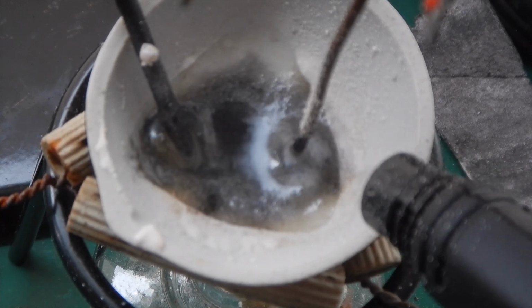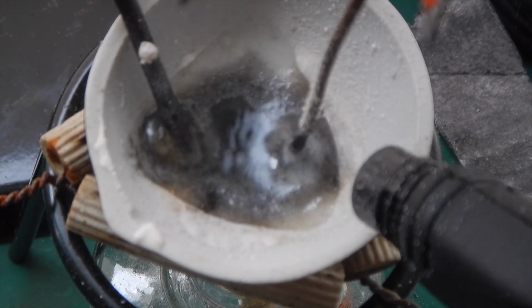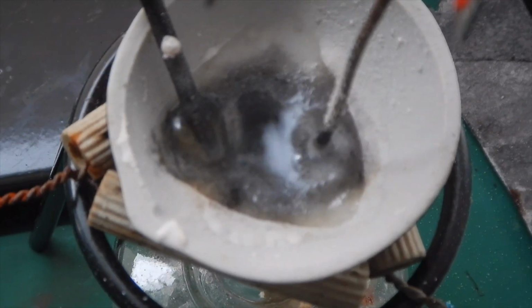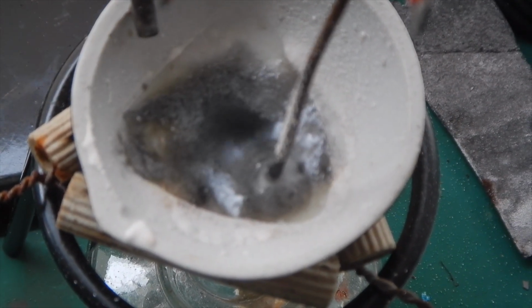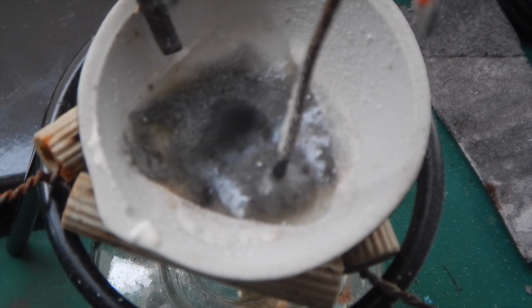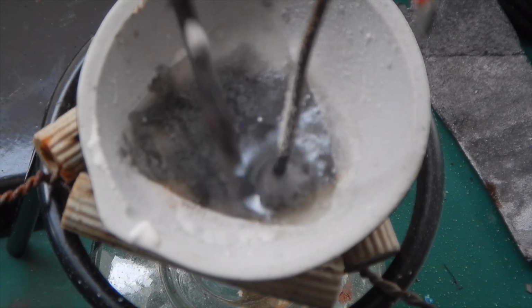You can see a few shiny beads of lithium near the cathode. However, I somehow decided to lift the carbon rod from the melt. This caused no current to flow through the cell, and the salt wasn't being heated enough.